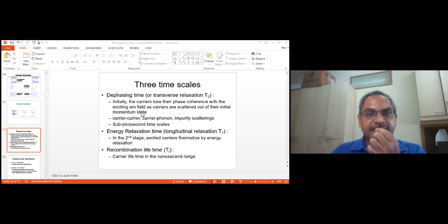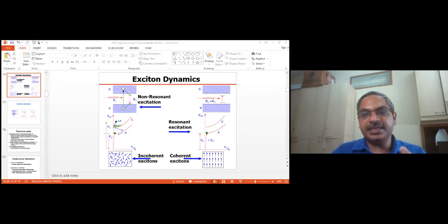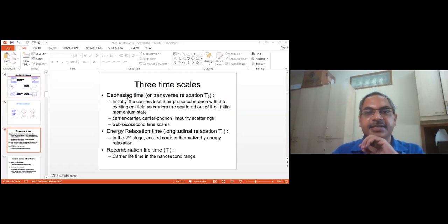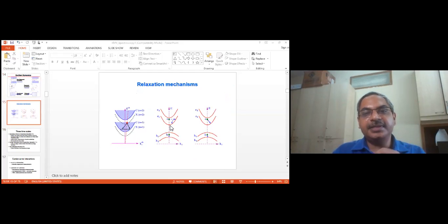measurements. So there are three time scales involved. The first time scale is how fast the coherence, the polarization of the excitons or electrons, is going to get lost to this incoherent exciton regime, incoherent electron regime. So all the polarizations are aligned in one direction, and over a certain time, they all become randomly oriented because they're scattering with each other. Okay? This scattering is going to randomize your polarization. So the first, the fastest time scale, is the dephasing time. The second one is called the energy relaxation time, where energy is lost, and then the recombination time, where basically the electron is going to recombine with the hole and emit a photon out, like the emission, the fluorescence which we see from the sample.